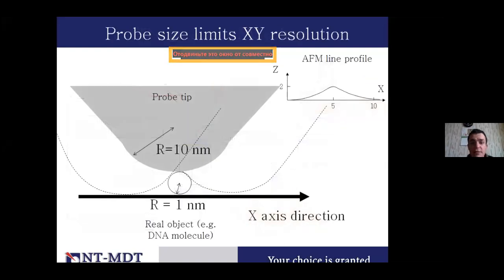And here is a description of the limitations of the general scanning probe sensor. The sensor is a tip on a cantilever, and it depends on the curvature radius. For example, in that case, it's like 10 nanometers. On the image, you can understand how our structure will look depending on the tip shape. For example, if we have a structure of 1 nanometer, and our tip has a radius of 10 nanometers, we always get the AFM profile like you can see on the top right. It will not be a round structure like DNA or a nanotube, for example, but you will see a profile which is limited by the probe shape.